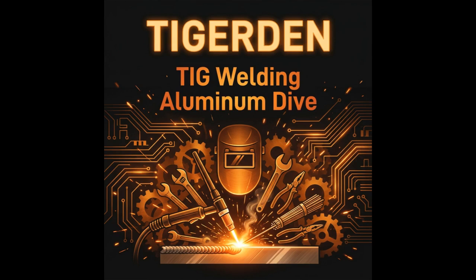It starts with the two-temperature trap. See, the aluminum itself, the shiny stuff, melts at about 1,200 degrees Fahrenheit. But it's wearing a protective suit of aluminum oxide that doesn't melt until you hit nearly 3,700 degrees. If you try to weld through that oxide without the right settings, you're basically trying to melt a chocolate bar inside a ceramic oven. By the time the oven melts, your chocolate has turned into a puddle on the floor. That's a messy mental image.